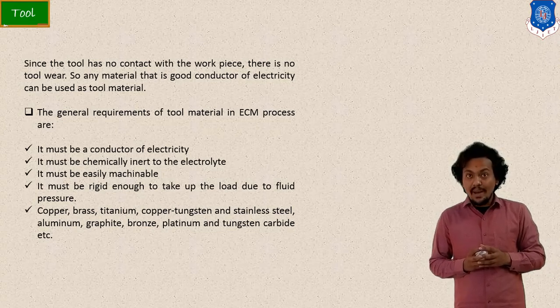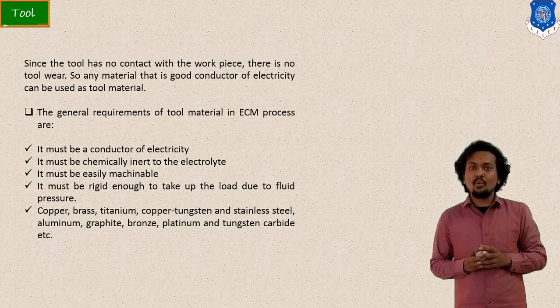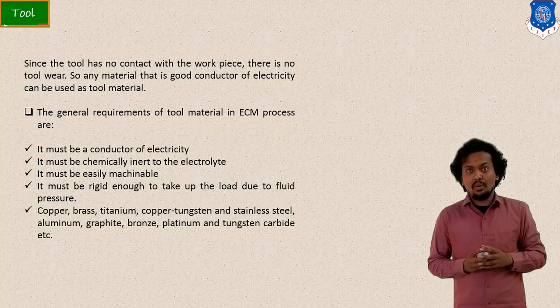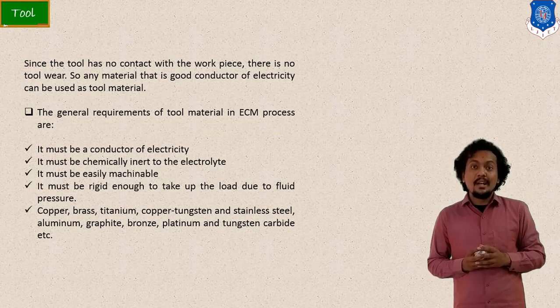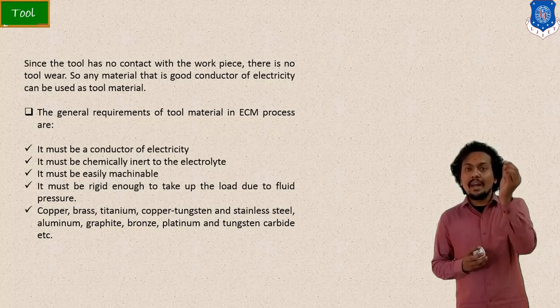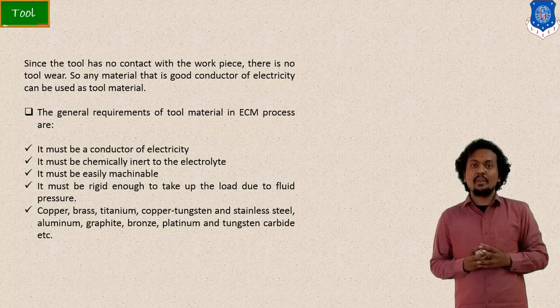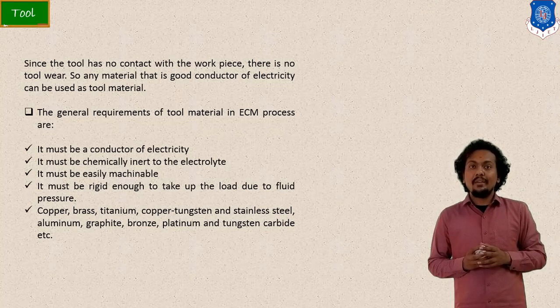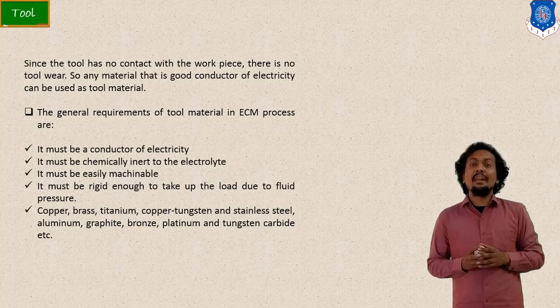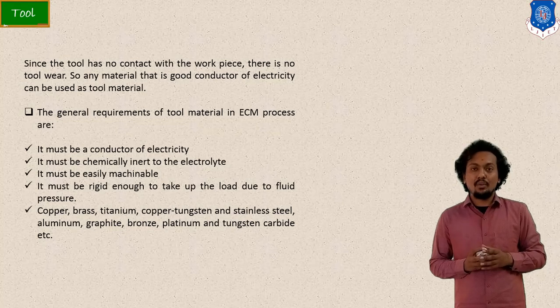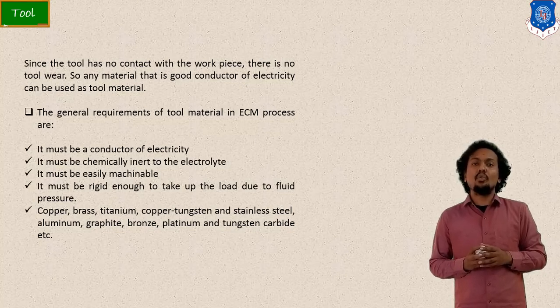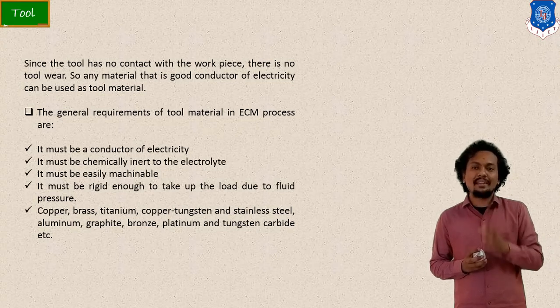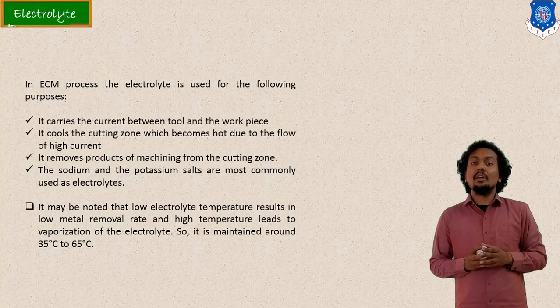The tool is very important and it should be electrically conductive. The purpose of the tool is that material from the workpiece tries to deposit on it, as the tool is connected with the cathode. Electricity passes through the tool material, so it must be conductive. The tool is designed as a hollow section so electrolyte can be passed through it. The tool should be strong enough to withstand the fluid pressure, electrically conductive, and easy to fabricate.